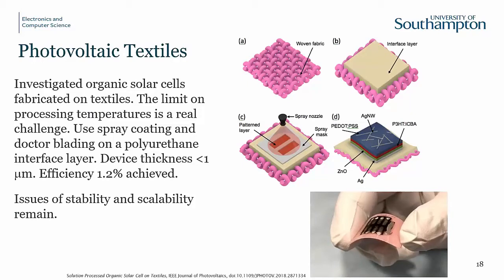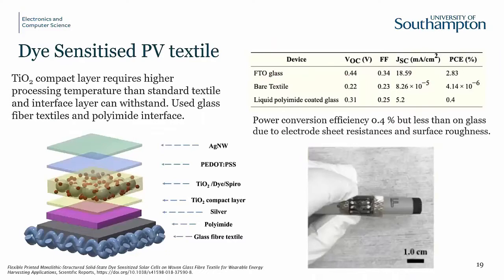And then we developed a spray coating process to build the thin film photovoltaics. And using organic materials, we were able to get up to 1.2% efficiency. Again, with all the processing constraints, no more than 150 degrees, for example, for any of the fabrication steps. So it works, but it's not particularly stable, and packaging this is an ongoing challenge to make it stable long term. We also looked at dye-sensitized photovoltaics, so electrochemical photovoltaic cells.